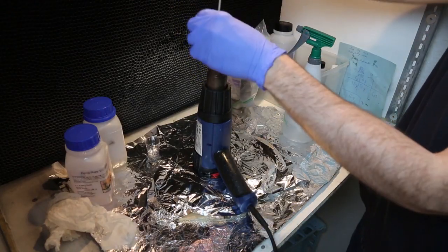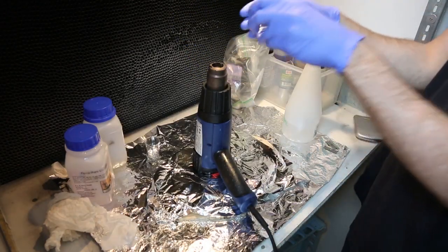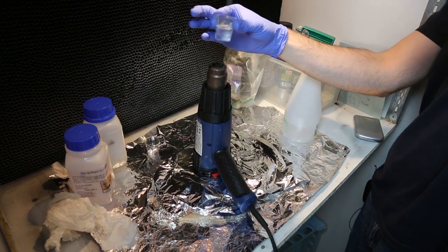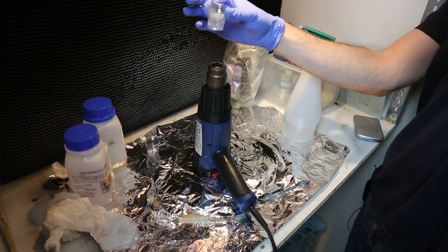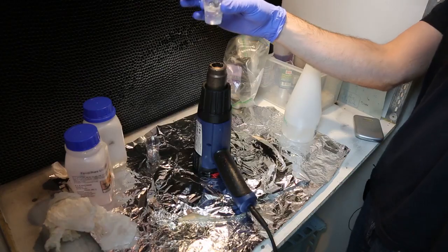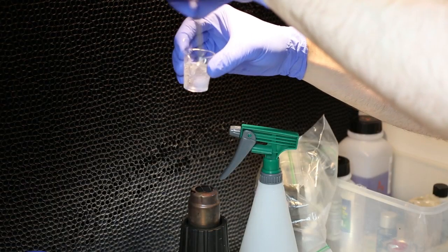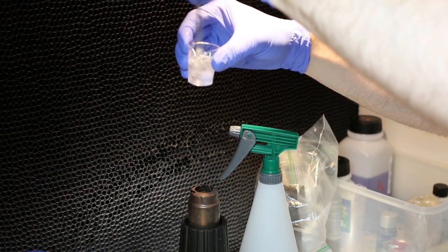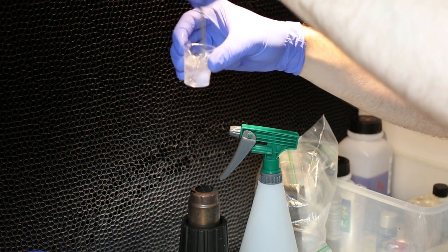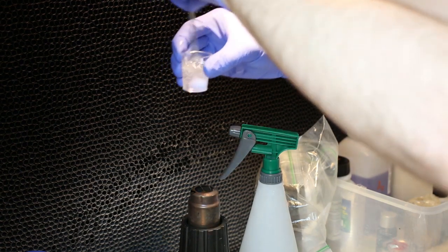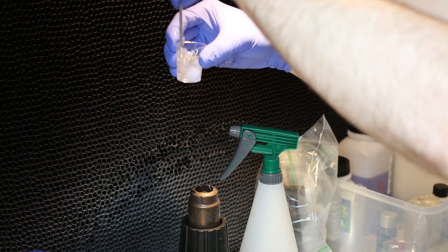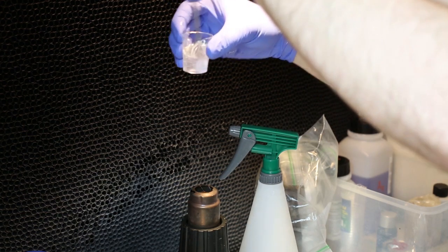I stir the glue for some time above the heat gun set to the lowest setting. Warm glue mixes much better than cold glue. If you want to get really fancy, you could also place the cup in a vacuum degassing chamber. That will get rid of all the bubbles created during mixing. Sadly, these are expensive, so I don't have one.